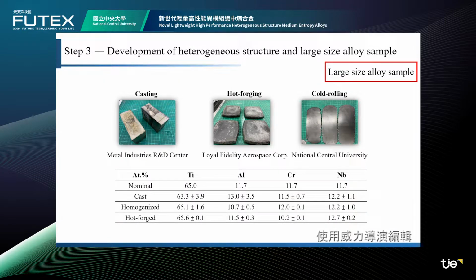In addition, we also use titanium 65 to carry out research on the commercial application of large-size alloy samples. We entrusted MIRDC to prepare the casting sample, while the hot forging was completed by Fidelity Aerospace, and the cold rolling was carried out at National Central University.